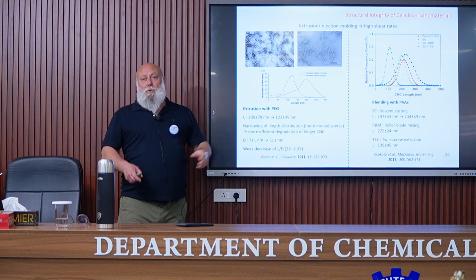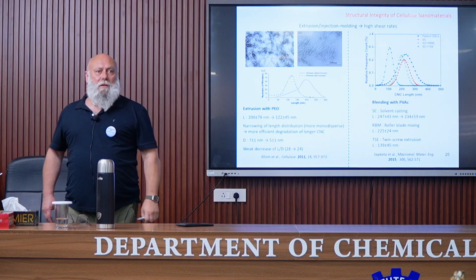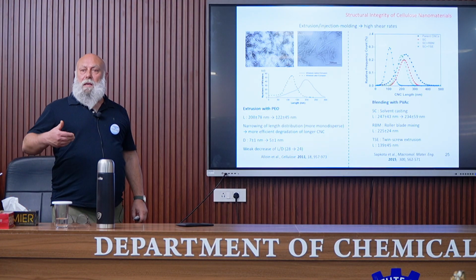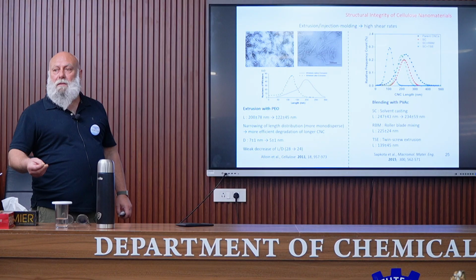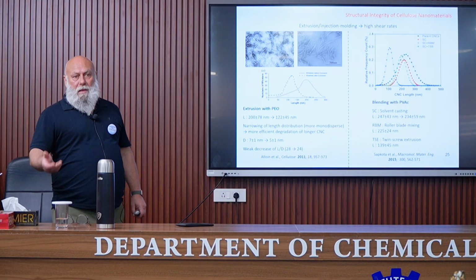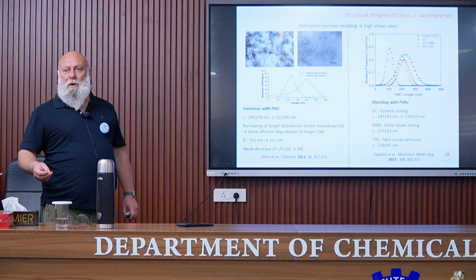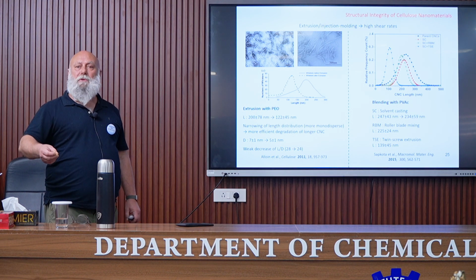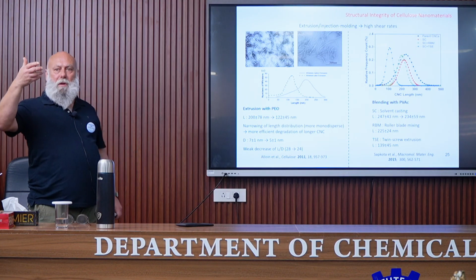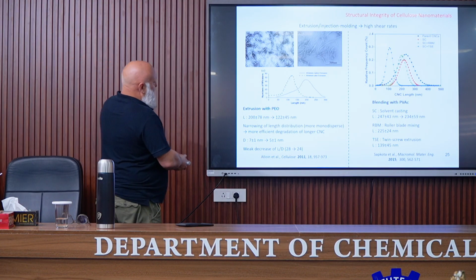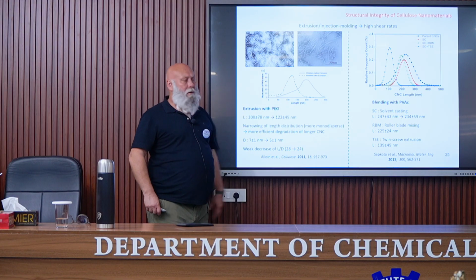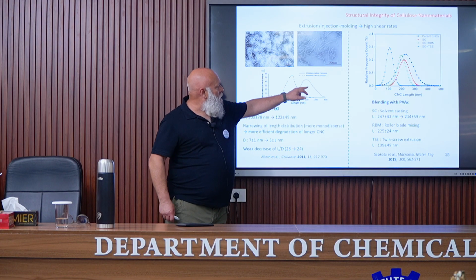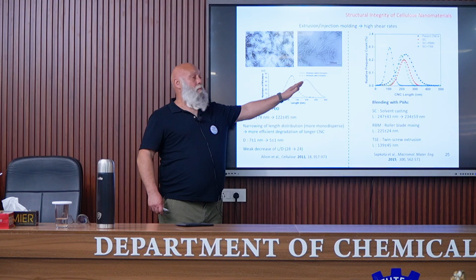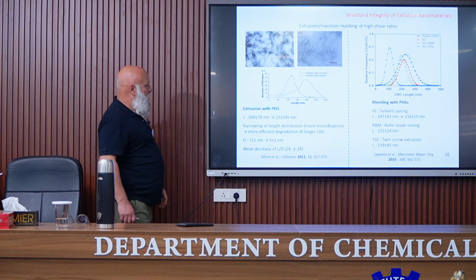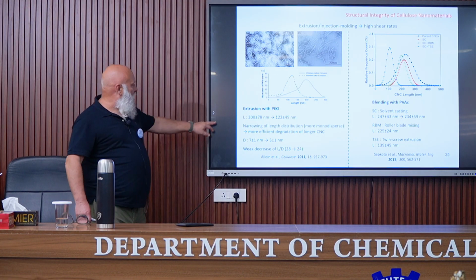They were extracted from ramie, and this is after extrusion. In fact, these nanocrystals were extruded with polyethylene oxide, and so it's quite easy to recover the nanocrystals after extrusion, because polyethylene oxide is a water-soluble polymer, meaning that the extruded composite can be dissolved in water and the nanocrystals can be recovered. This is the length of the nanocrystals before and after extrusion. We can see that effectively the nanocrystals were broken.